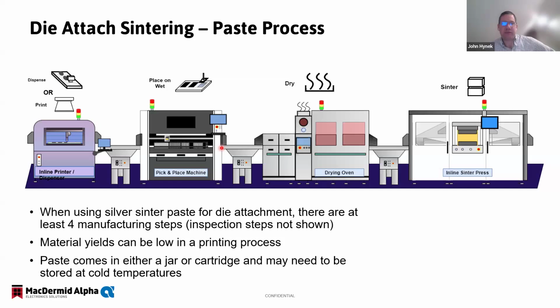And then you have a choice with your next operation. You can either use your pick and place machine and place the component on the wet sinter paste and then dry it, or you can dry it first and then place the component dry. The last operation you're going to have is the sinter operation. So you've got at a minimum 4 steps you have to be concerned about, 4 different pieces of equipment. I mean, obviously you can integrate them, but 4 discrete steps and possibly inspection steps in between to make sure that your dispense operation was okay and that you don't have excess voids, excess marks, or an inappropriate dispense where you're not on plane.